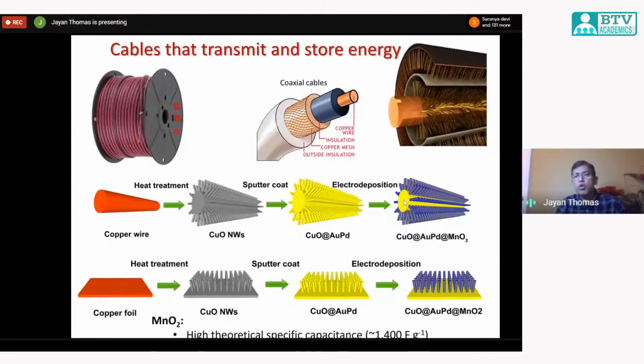Remember, the inside is still copper, but the inside copper is insulated from the outside because of the presence of nanowires. Then for the other electrode, we just took copper foil and heated it to a higher temperature, and you can see that the copper nanowires are formed. Then we deposited gold palladium onto it, and here is the copper oxide, gold palladium, manganese dioxide. Then we took this one internal wire and wrapped that internal copper wire with this outside copper foil to get a supercapacitor.